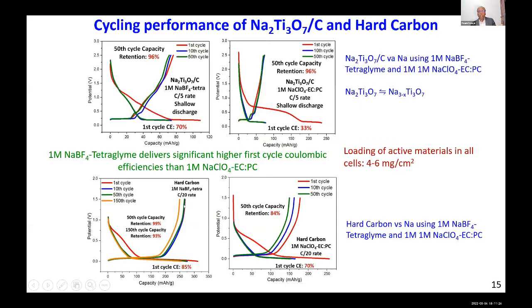You can see the performance in hard carbon. Hard carbon is a well-known anode material used for sodium-ion battery technology. You can see here I'm using carbonate-based electrolyte, NaClO4 in EC ethylene carbonate, PC propylene carbonate. The performance is not that impressive. It has a Coulombic efficiency, that means insertion of sodium and extraction of sodium, if you look at the ratio, it is about 70%. And the cycle life is also not so impressive. Under the same testing condition, if I use tetraglyme, I can get about 85% Coulombic efficiency, which is very good. And the cycle life is also pretty good.